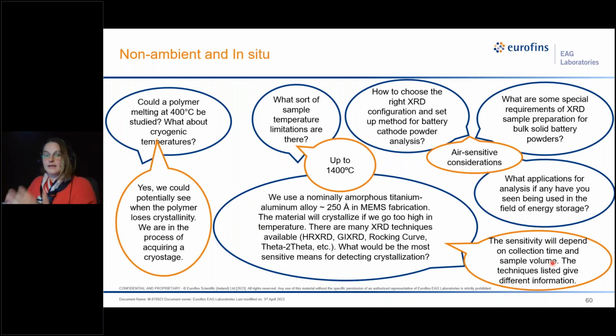Now, non-ambient and in situ situations. We have a high temp stage that goes up to 1400 degrees C, and a lot of people are very interested in XRD for battery applications. So we can analyze the cathodes, the anodes, any of the building materials of the battery. We're actually in the works right now to get an in operando stage for a coin cell, so we can essentially be cycling the battery while we're collecting the diffraction. But right now, even without that, we can do battery components.